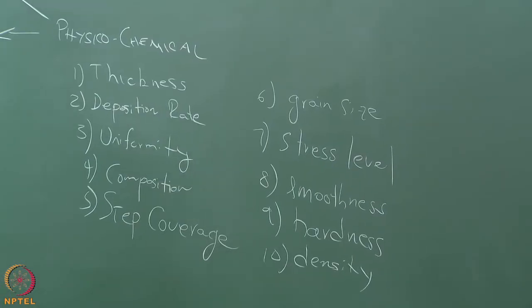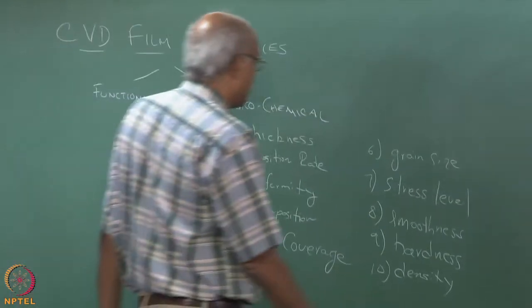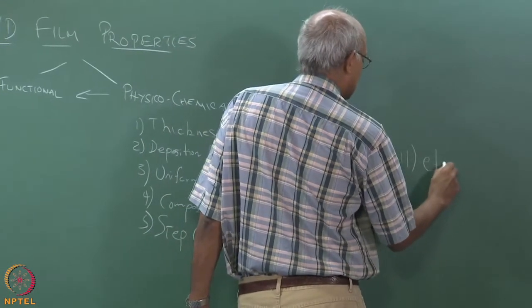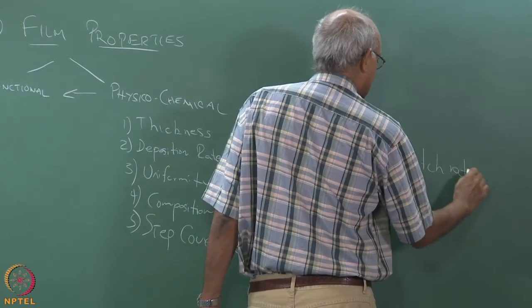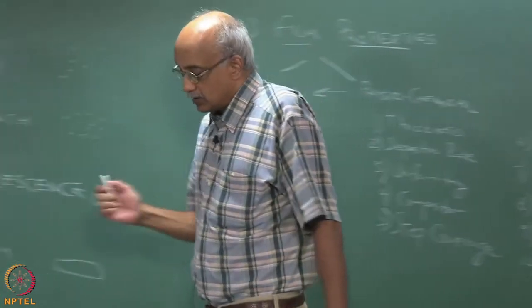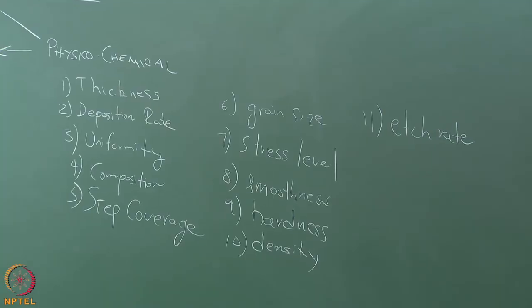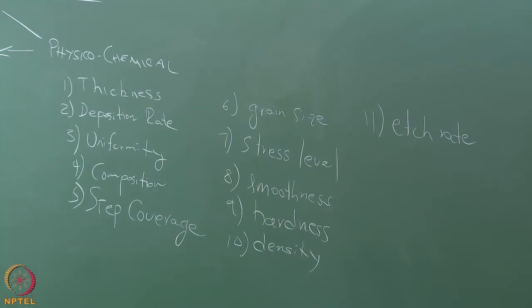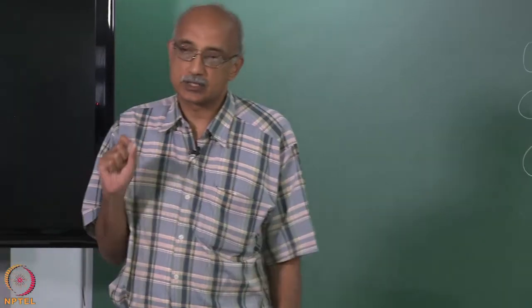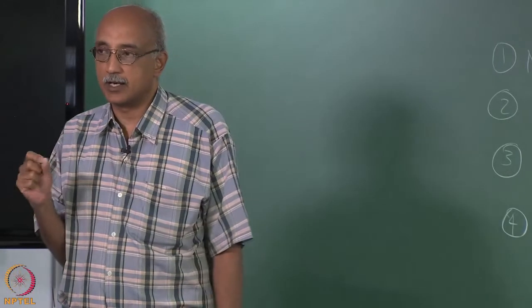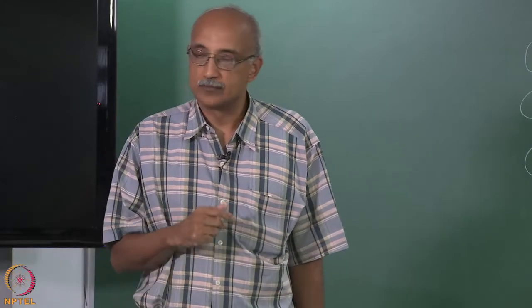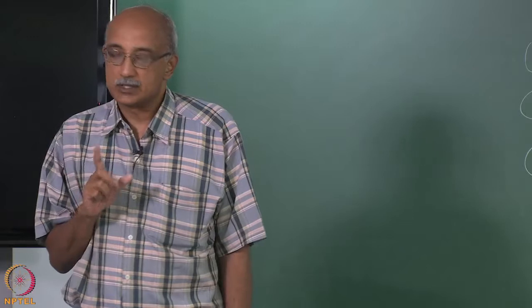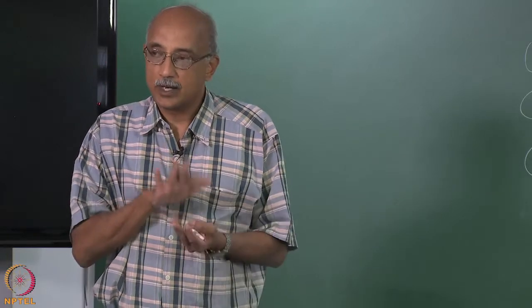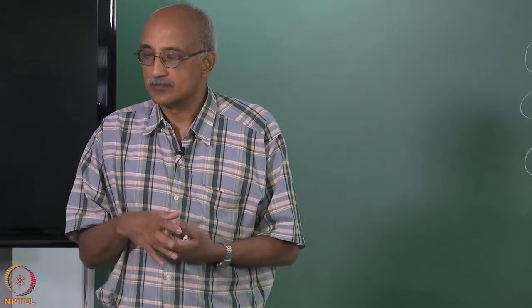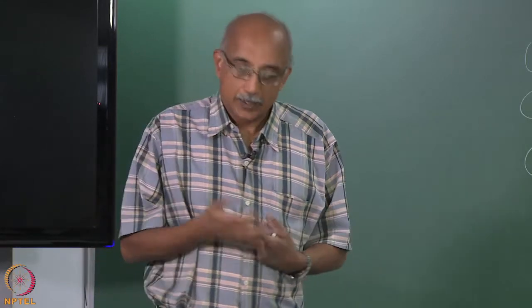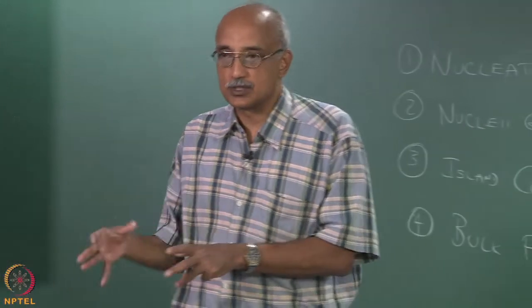Actually, another parameter that is frequently measured on CVD films is called the etch rate. So what's done here is you take the film and expose it to hydrofluoric acid and you measure the rate at which the film is being etched by hydrofluoric acid of a certain concentration. The rate of etch of the film is a very good indicator of how well integrated the film is on the surface. So essentially the higher the etch rate, the less strongly adhered the film is to the surface.